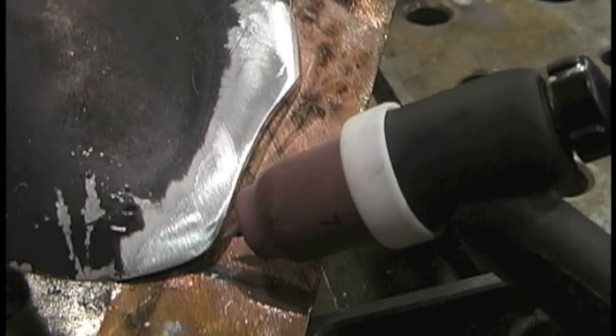I extend my electrode out a little bit further than I need to for the sake of filming here, but that's not too far. And again, I light up and let it puddle. Let the cleaning action work just a little bit before I get crazy with melting it. Make sure it's going to puddle cleanly and nice and shiny wet. And then I just do just like I did on that little mock-up a minute ago. I just watch the front edge of the puddle, use just enough amperage with the foot pedal so that it wets in, but doesn't fingernail and cut in real deeply, because I just want to build up. Once I melt that first molecule, anything else is just kind of more than enough. I would like to weld it hot enough to wrap around the bottom edge as well and wrap around the top, but that's all it takes.